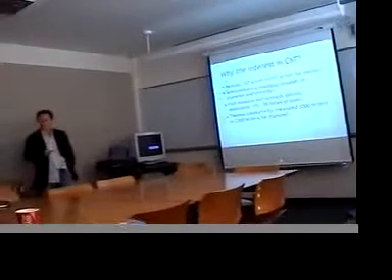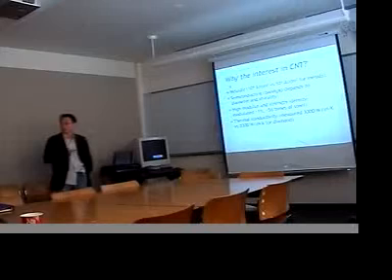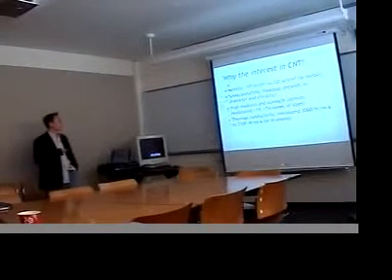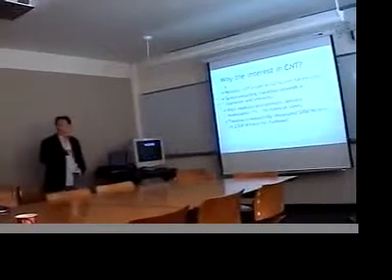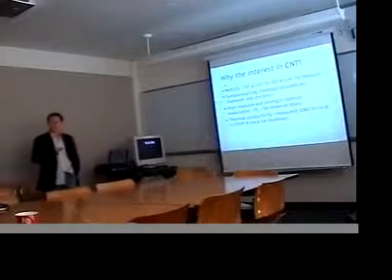For metallic CNT, they have very, very high current capacity. The highest, I guess, typically the agreed upon value is around 10 to the power of 9 ampere per cm square, as opposed to copper, which is probably one of the most conducting metals. It's only 10 to the power of 5. So you see a 10,000 times increase. So researchers have been trying to explore carbon nanotube as an interconnect in normal circuitry.